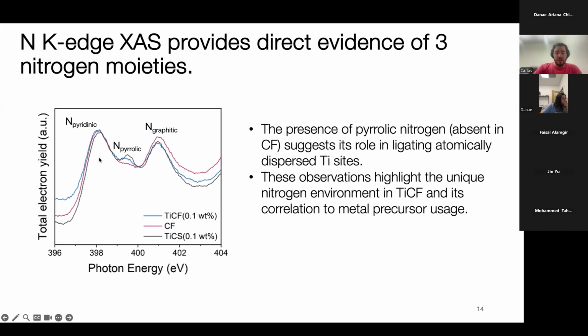You can see that the pyridinic and the graphitic peaks for nitrogen are present in all of these curves, but the pyrrolic peak of nitrogen is only present in the titanium doped species. So that is sending us in the direction that we think that the titanium is ligating atomically to these pyrrolic nitrogen sites.